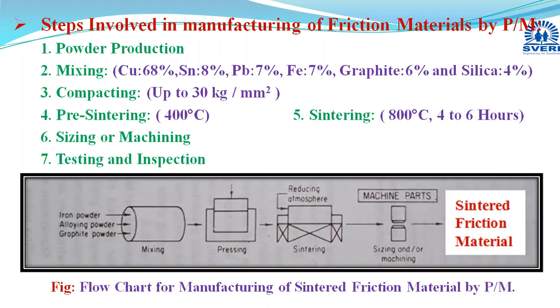And due to the diffusion, older grains are broken and formation of new grains takes place, and their development occurs, which is termed as recrystallization and grain growth process. And all these three stages, that is diffusion, densification, recrystallization, and grain growth, complete in this 4 to 6 hours time of sintering at 800 degrees Celsius temperature, which is conducted in this reducing atmosphere.